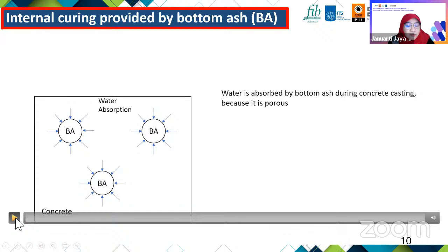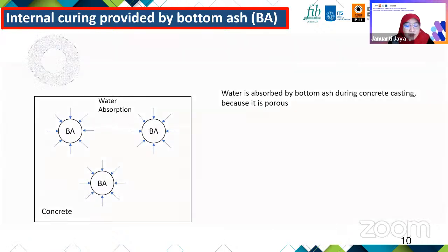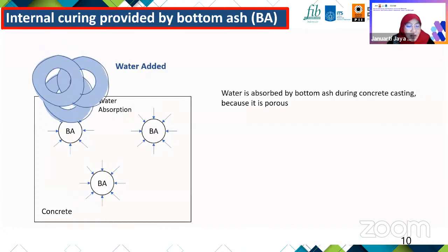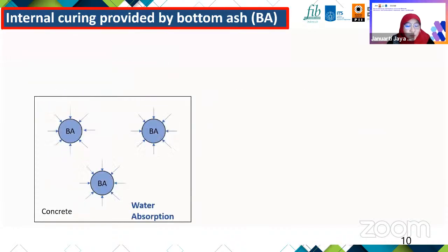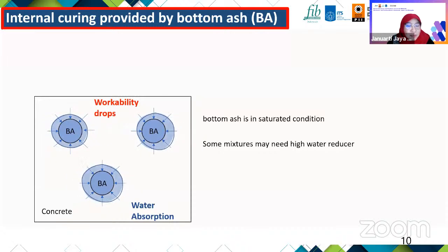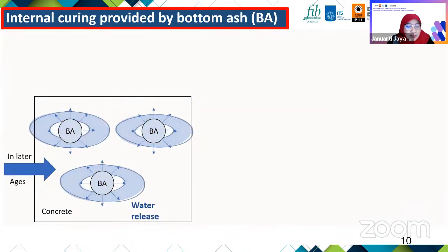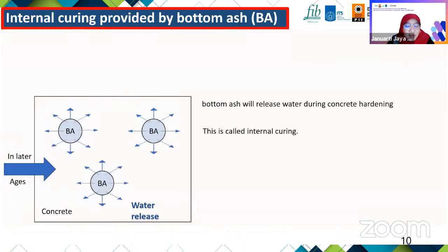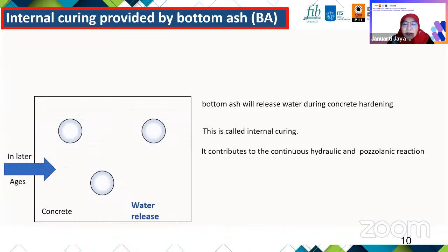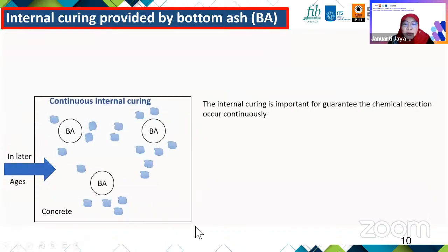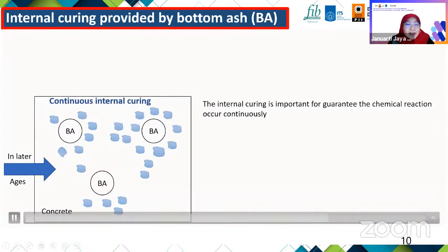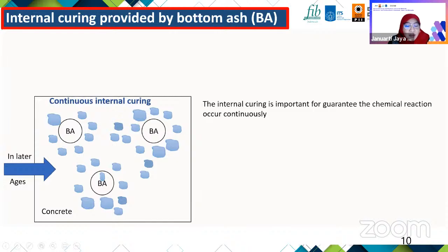And this is, I have also the schematic simulations. This is the internal curing effect from bottom ash that we expect to occur during the hydration of the concrete. It works as a sponge. It absorbs water at the beginning to lower the water to cement ratio and maybe lower the workability. But then it releases moisture gradually at the later age. So this is called internal curing. So it contributes the moisture to guarantee the next chemical reactions because of the pozzolanic reaction and because of the bacterial activity.